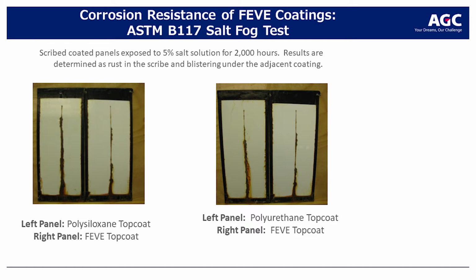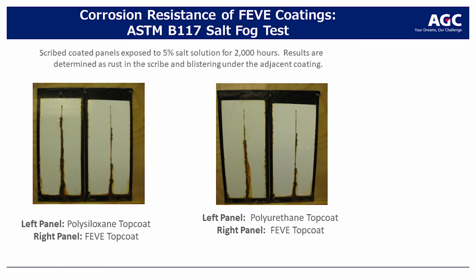So this is one of the tests we run. This is the ASTM salt fog test. They take these, in this case, it's a 5% salt solution. They run it for 2,000 hours in a testing cabinet where they spray the panels with the salt. And what they do before the test is they scribe the coating. They scratch the coating down to the metal surface. And then really what you're looking for is rust in the scribe. How much did it rust? And then you're looking at how much does it undercut? How far does it go under the coating?